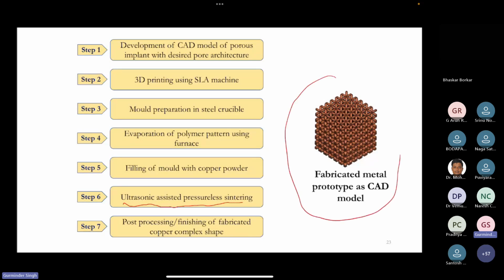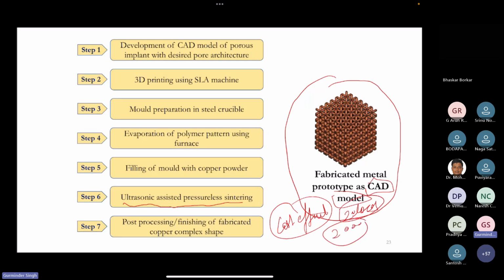After sintering with the assistance of ultrasonic vibration and high temperature, you can get a 3D printed metal part which has the same shape as the CAD model. This process is very cost effective. You can make the whole setup in a few lakhs, 2 lakhs, 3 lakhs, depending on the quality of the accessories. If you are buying a copper part for 10,000, you can make a 20 by 20 lattice structure for only 2,000, which would be around 15 to 20,000 when making it with a laser based system.